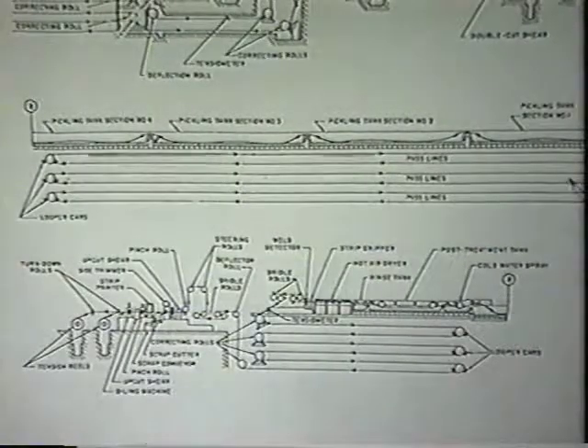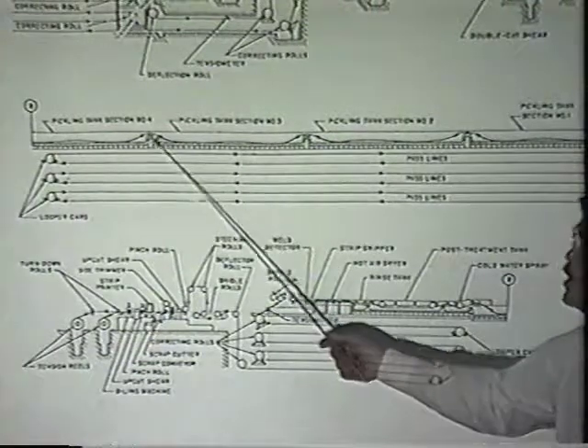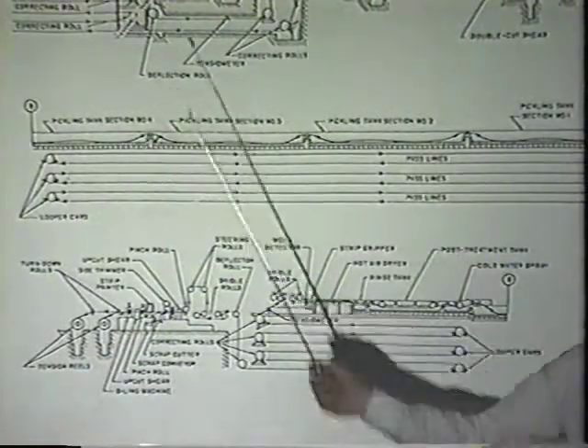We'll come out of the looper storage area and into the pickle tanks. Here we have 4 tanks. They're brick lined. They contain hydrochloric acid. Each tank has a little different pH to it, a little different iron concentration to it. It all is involved in the science of pickling. The key here is to keep the strip moving through the tanks without stopping. If the strip stops in the tank, the acid, once it finishes eating the scale away, will start to attack the strip. That's a condition we call over-pickled. It looks like the strip is etched. It's basically, for cosmetic type applications, unacceptable.